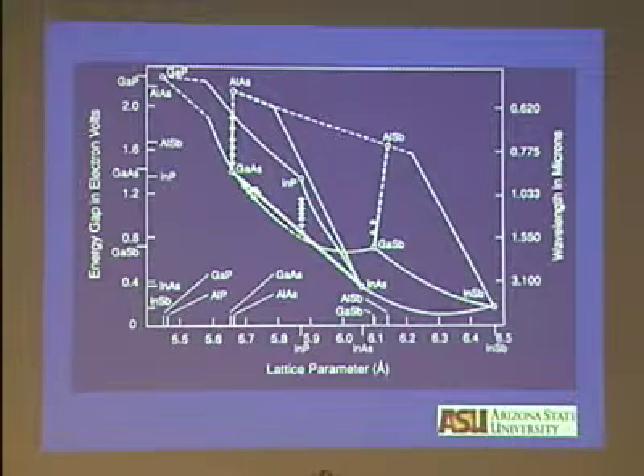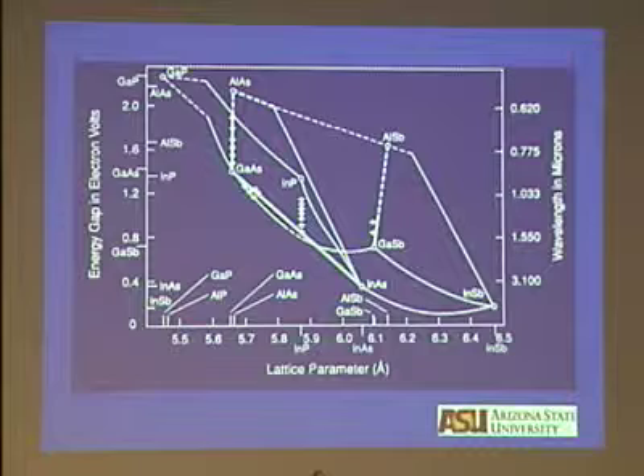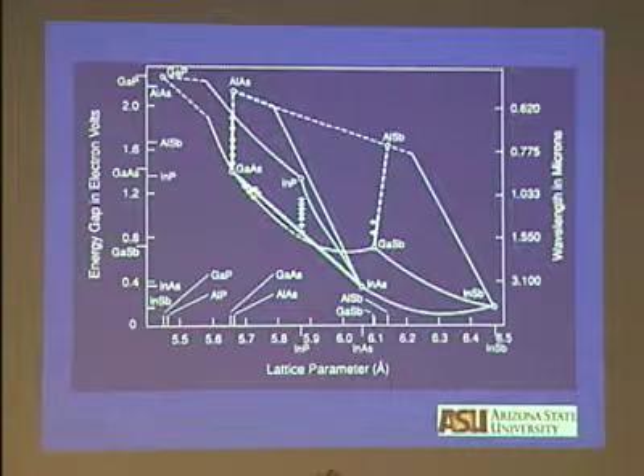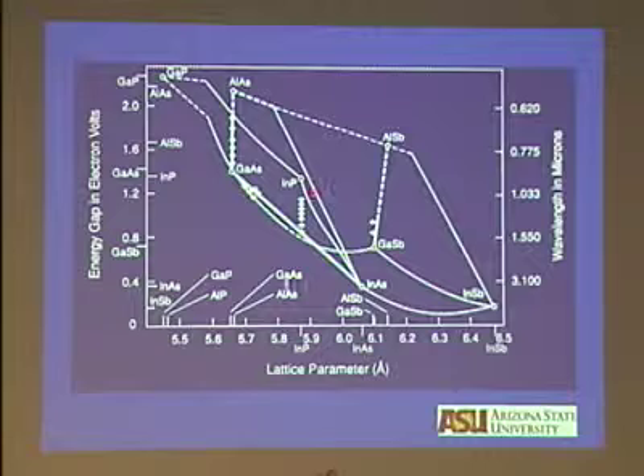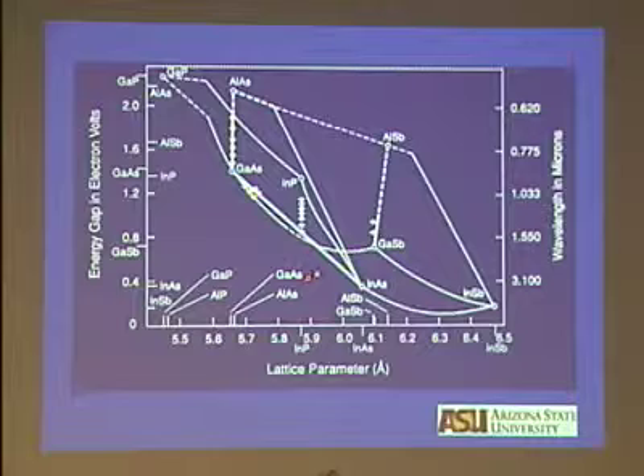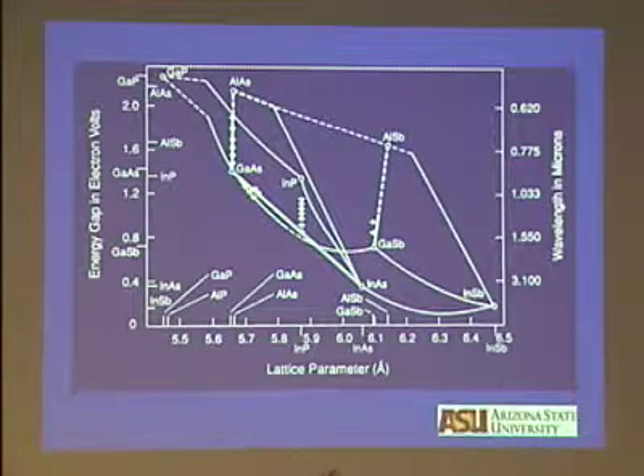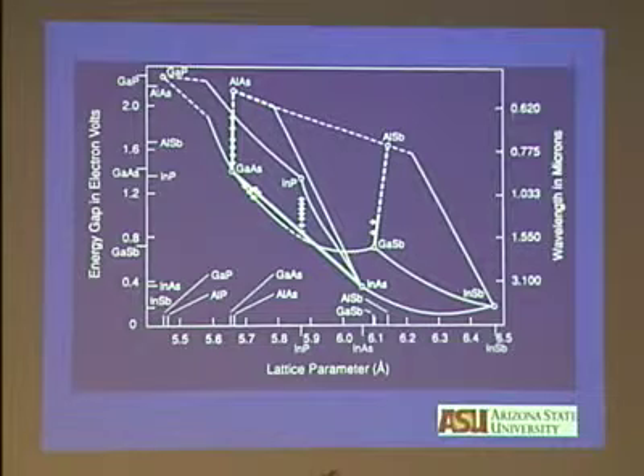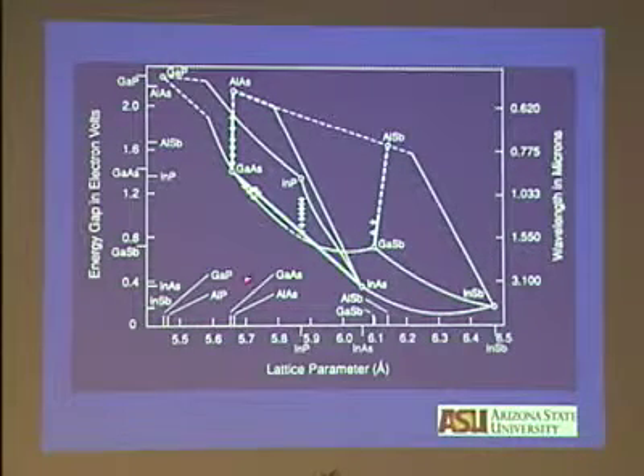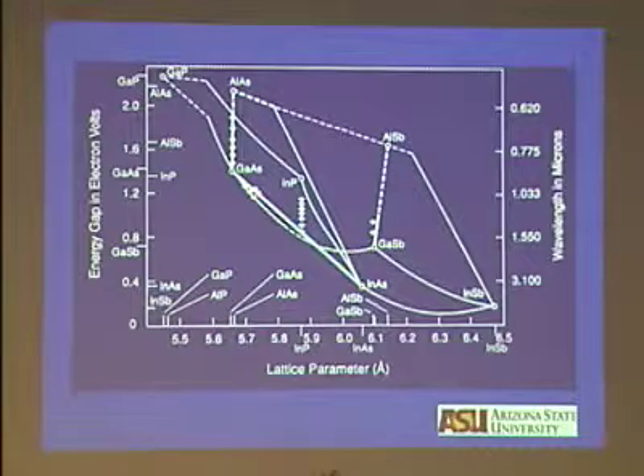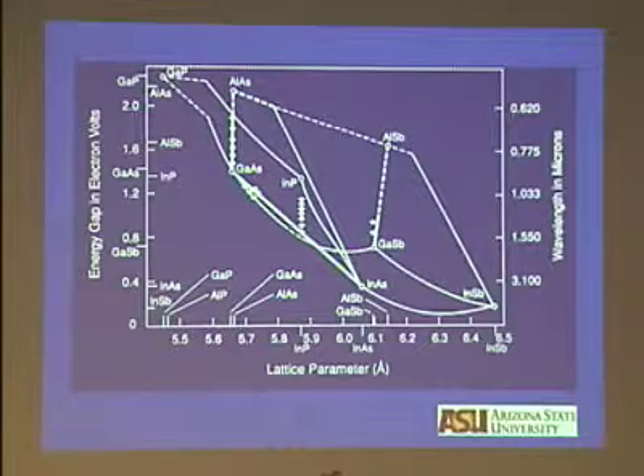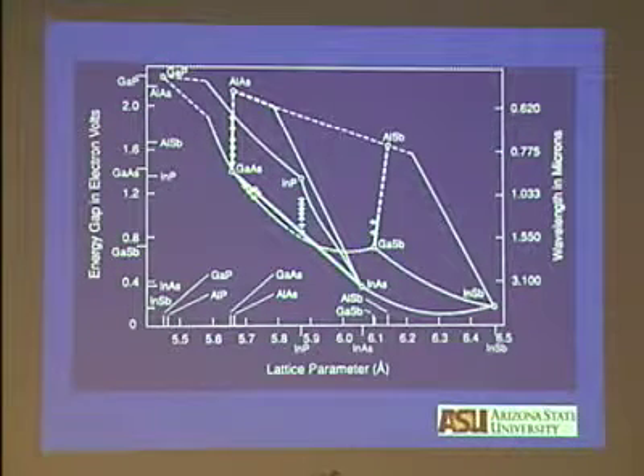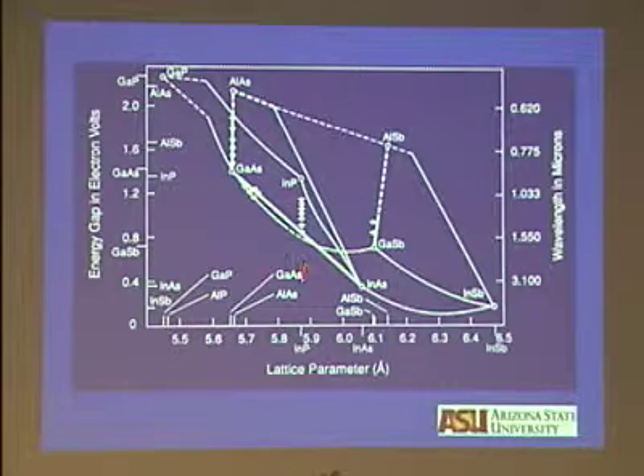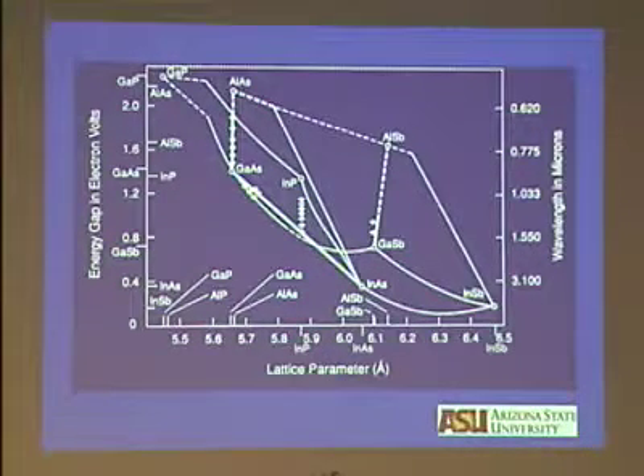Look at indium phosphide. We didn't create these materials, they exist in nature. And you can change the band gap of indium phosphide when you mix it with gallium arsenide. The beauty is that this remains lattice matched to the underlying substrate. So you can make light emission devices which will emit at 1.33 or 1.55 microns. You can make detectors in these materials which will absorb at 1.55 and still be lattice matched. And these devices are used in light wave communication.